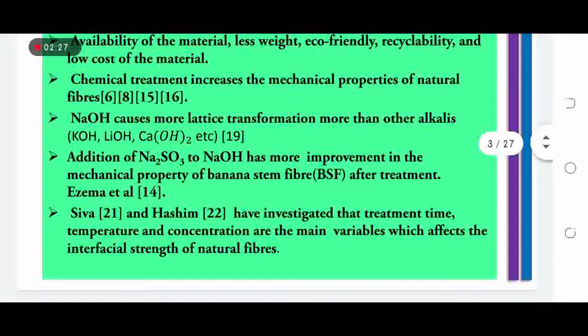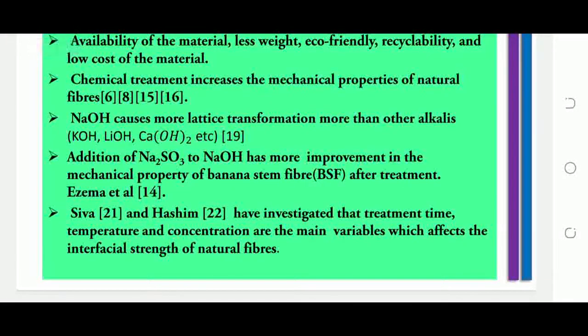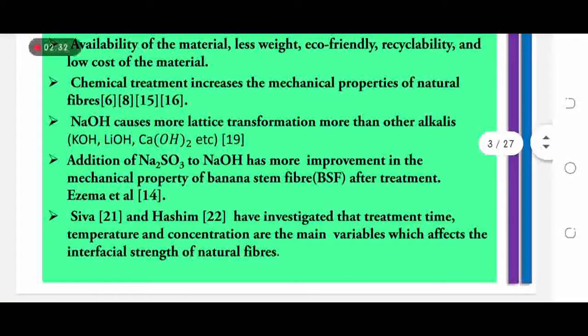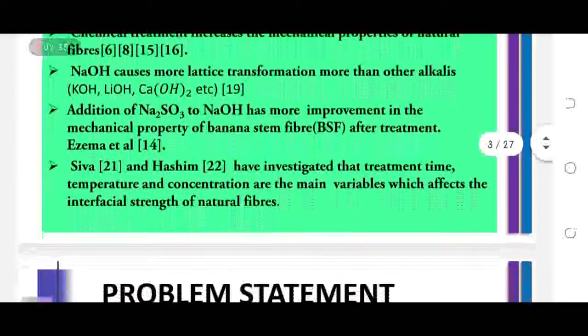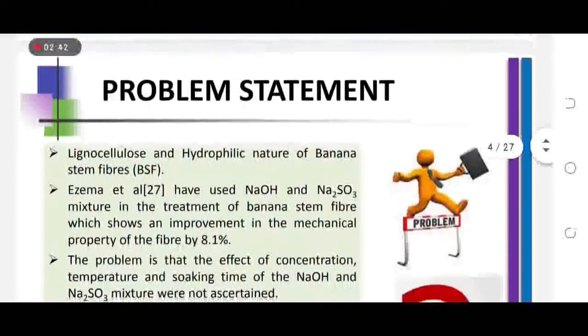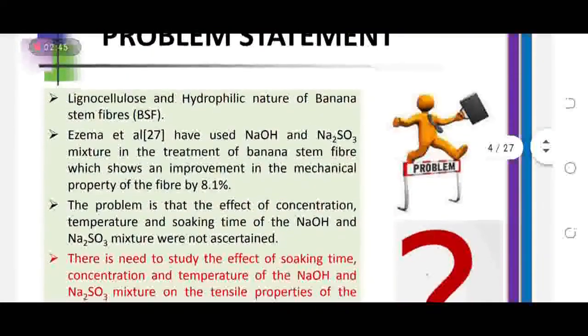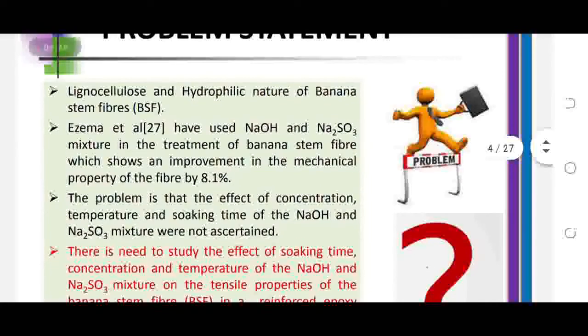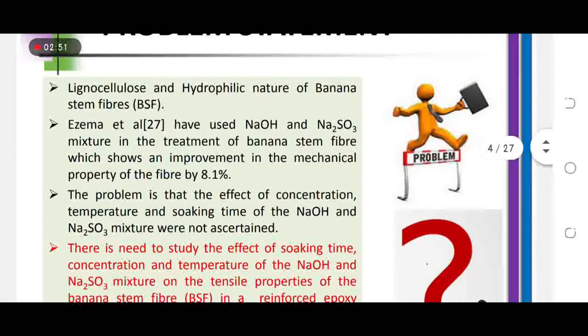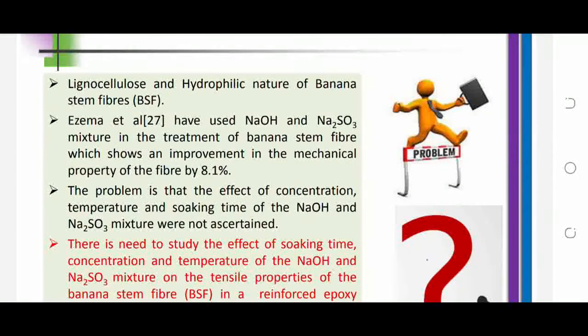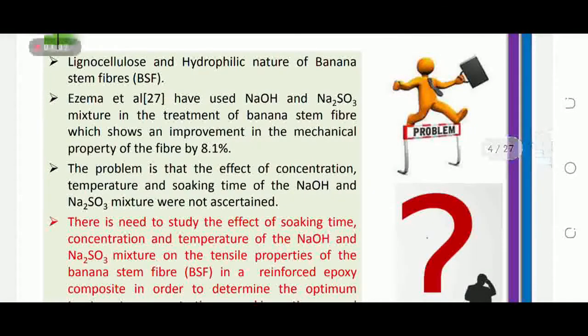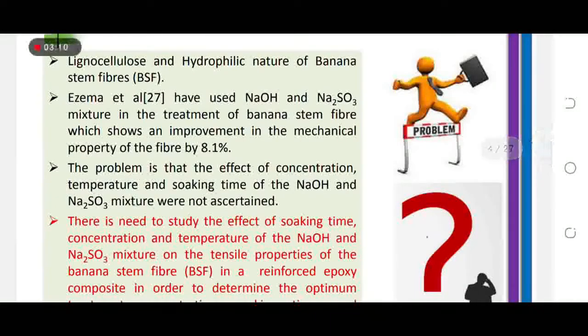Siva and Hashim have investigated that treatment time, temperature, and concentration are the main variables which affect interfacial strength of natural fibers. The lignocellulose and hydrophilic nature of banana stem fibers is what hinders them from being used as a reinforcement material in composite, because they absorb moisture and there is no interfacial bonding between the fiber and the matrix. So Ezema et al. have used sodium hydroxide and sodium sulphite mixture in the treatment of banana stem fiber, which shows an improvement in the mechanical properties of the fiber by 8.1%.